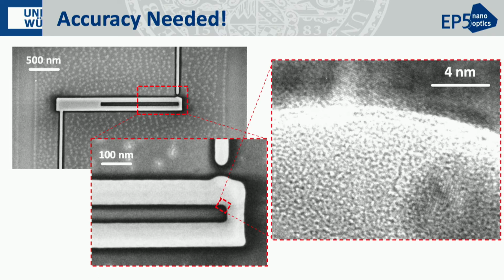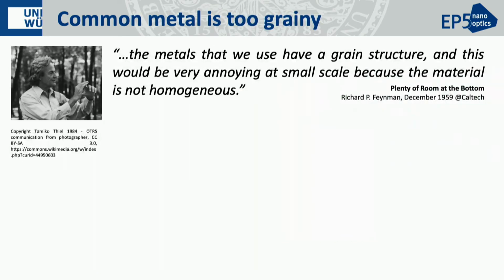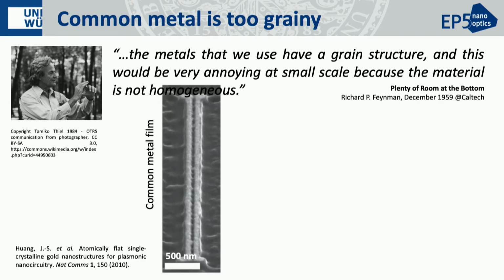And this is actually not only a fabricating problem, but also, again, a problem from the starting material, because common metal is rough and grainy on the nanoscale. This is something already Feynman mentioned in his talk 60 years ago. The metals that we use have a grain structure, and this would be very annoying at small scale because the material is not homogeneous. When we now use a structuring method, like in this case focused ion beam milling, to build such a structure out of common metal films, you can see that they are quite rough and not really homogeneous. And this is really inherent to the starting material we use for our structuring.